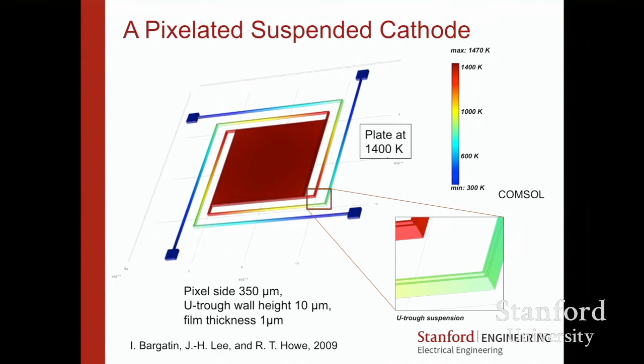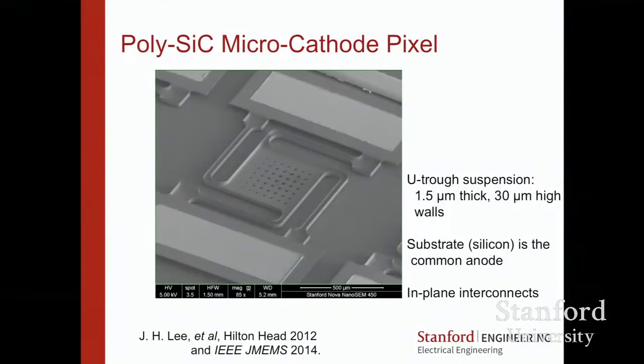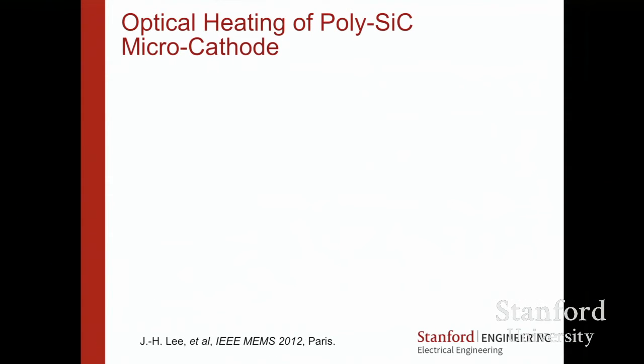Will it work? Well, we made something out of a material that's not a very good cathode, but it's a good platform. This is silicon carbide, LPCVD silicon carbide. It wasn't done in the Stanford nanofab because we don't have a silicon carbide tube, but it is available in Berkeley. So this grad student went up there, and you have this structure that's certainly suboptimal. The lithography isn't great, but it certainly is thermally isolated, and we optically heated it.